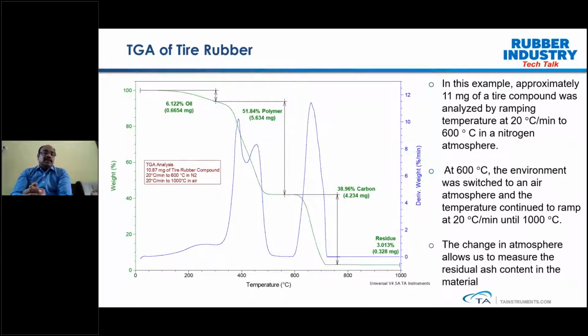So what we observe is, on the x-axis is temperature, and the y-axis on the left-hand side is weight percentage, and then the y2 axis, on the right-hand side, is the derivative weight. As we heat the sample, we start from 100%, and the sample starts decomposing. At a lower temperature, we can see the low-temperature volatile oil components start coming out, which accounts for 6.12% of weight change.